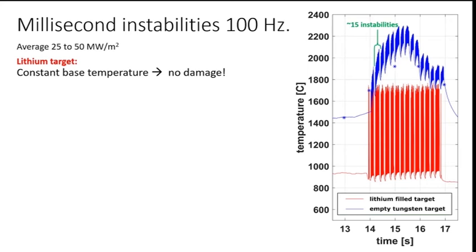What you can see, the lithium target in red, is that the base temperature stays more or less constant. The temperature peaks are very high, but actually we think that is because the infrared camera is picking up emission from the vapor cloud rather than the surface. So we expect this temperature rise on the surface to be much less. And there's no damage, which we also could observe afterwards. So these samples survive perfectly.